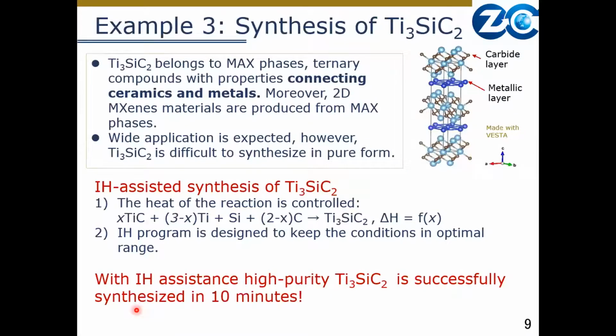And finally, let me explain about synthesis of titanium-3 silicon carbon 2. This titanium-3 silicon carbon 2 belongs to MAX phases. MAX phases are ternary compounds which have properties in between metals and ceramics. So they have merits of both metal and ceramics. For example, this MAX phase has high electrical conductivity as a metal, and it's machinable. It can be shaped in different forms. Moreover, MAX phases serve as sources for two-dimensional MXene materials, which are widely used in various fields. So wide application of MAX phases is expected.